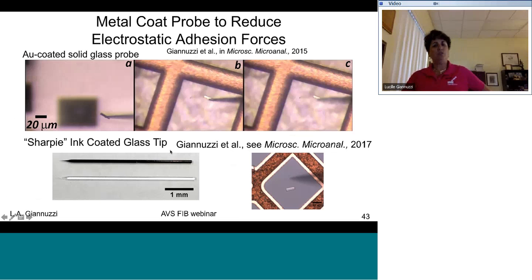And in fact, what you want to do is totally avoid electrostatic forces. And the way you can do that is to just metalize the glass tip. You can do that by either metal coating the glass tip, or by using the Sharpie ink again, as we learned before. So just use a permanent marker ink and just coat the tip, and this totally avoids electrostatic forces, increasing the van der Waals forces.